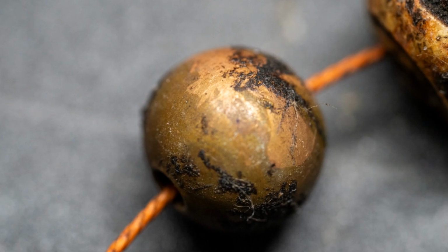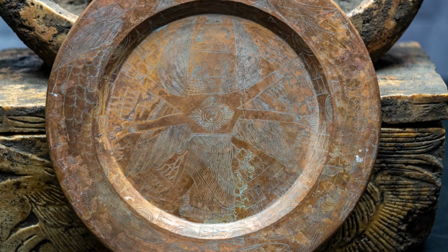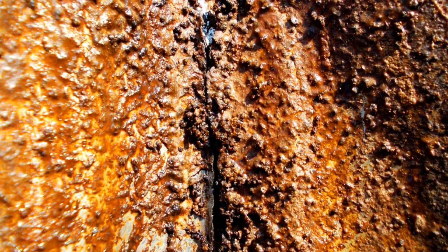These are typically small, hard, and sometimes crystalline deposits of various copper corrosion products like malachite or azurite. These specific features clearly show that the chemical changes on the metal surface happen slowly, progressively, and have penetrated deeply into the material. They are not merely a superficial coating that has been applied to the top. These are considered strong and reliable indicators of authentic, prolonged aging processes. Such intricate and microscopic details are exceptionally difficult for forgers to replicate with any degree of accuracy.